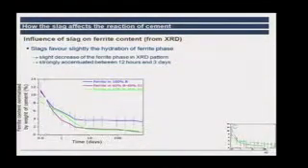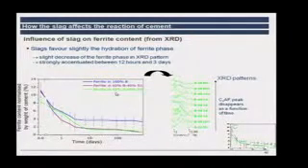On the contrary to that, if we look at the ferrite phase, you may remember that the ferrite phase was reacting up to about 80%, and now the ferrite phase seems to be much better reacted in the presence of slag, so that we really can't see any trace of the ferrite peak. This is the ferrite peak, and you see here by about, certainly by 90 days, this has completely disappeared. And this is the case in terms of all the different cements.